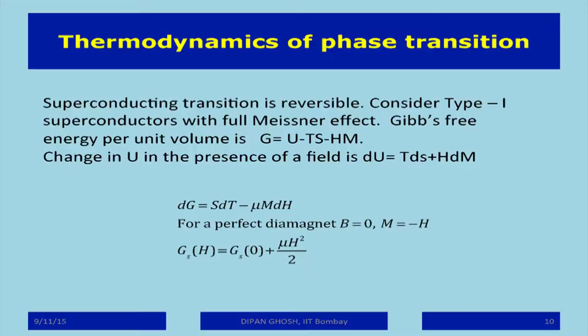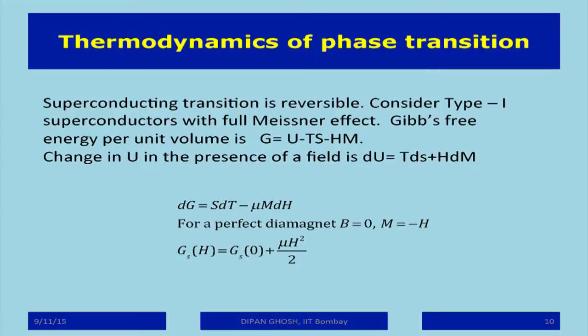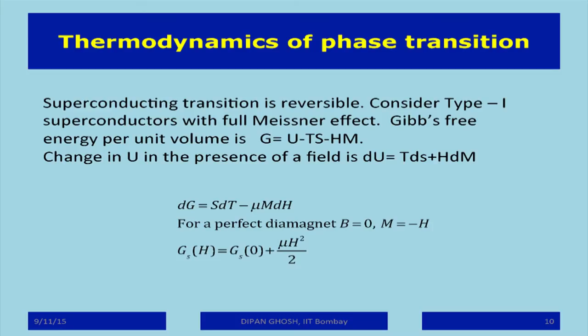Okay. Now, if I have a perfect diamagnet, then B is equal to 0. Therefore, M is equal to minus H. Remember that for a perfect diamagnet, the susceptibility is minus 1. Now, in that case, I can get an expression by integrating this of the Gibbs free energy as a function of the applied magnetic field. So Gibbs free energy as a function of the magnetic field is some GS0 plus mu H square by 2. This is the same as B square by 2 mu if you are using B. Okay. So that is the energy of the system when it is in the superconducting state.